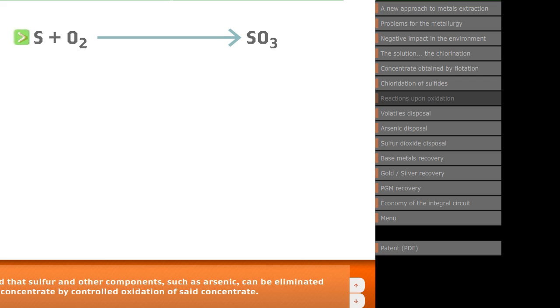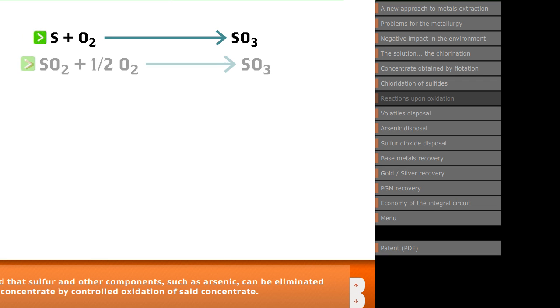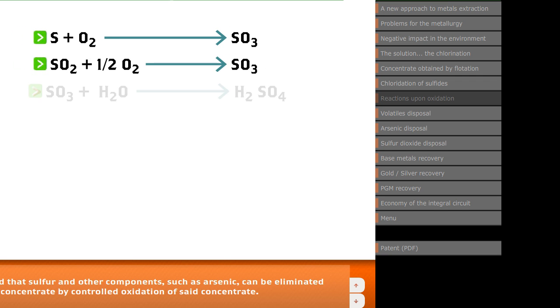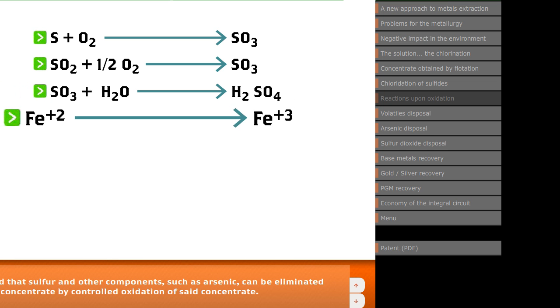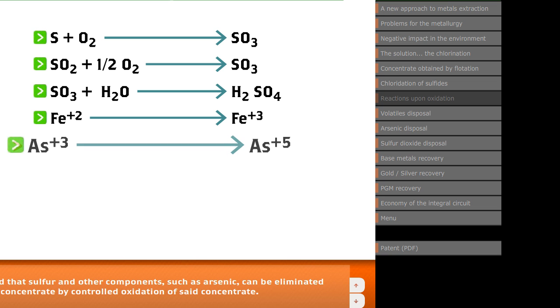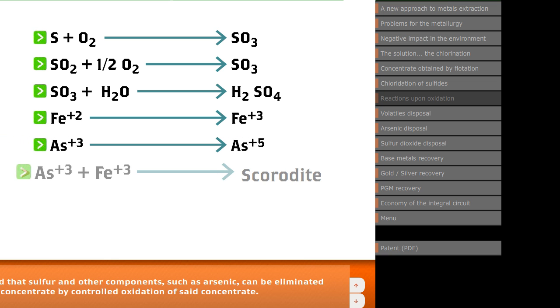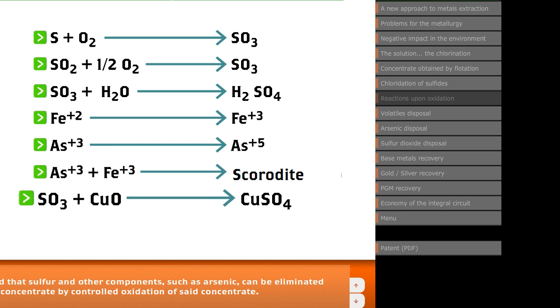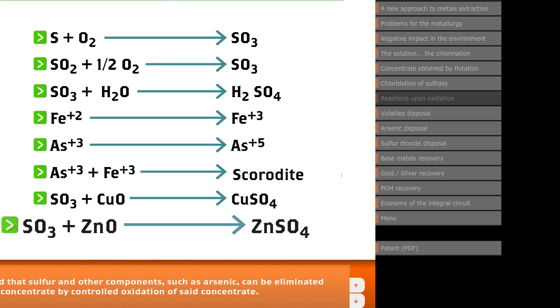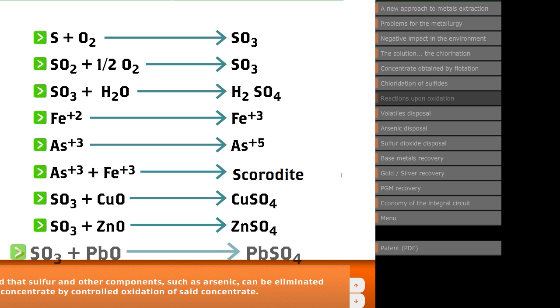It has been found that sulfur and other components, such as arsenic, can be eliminated from the sulfide concentrate by controlled oxidation of said concentrate. Controlled oxidation is not roasting. Roasting or burning of sulfides with free access of air has a well-deserved bad reputation from its very detrimental impacts on both health and environment. Also, roasting because of its high temperature can induce sintering of the ore and make it refractory to metal extraction.